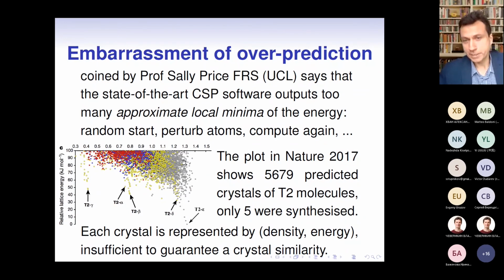So that's why, for example, in this plot from the Nature paper by our colleagues in the Liverpool Materials Innovation Factory, you see almost 6,000 predicted crystals based on the T2 molecule from the previous slide, but only 5 actually were physically synthesized in the lab. And in this plot, each crystal is represented by only 2 numbers, density and lattice energy on the vertical axis. So of course, these 2 numbers are too simple and insufficient to guarantee crystal similarity. So many crystals here look very similar, nearly identical, but only because the density and energies are similar, not necessarily crystal structures. That's why we need more invariants, so better tools.